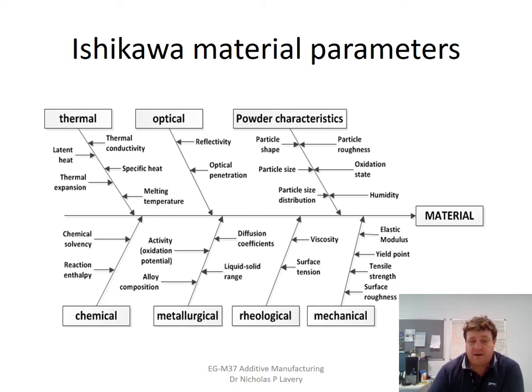Obviously, the chemical and metallurgical aspects of what type of alloy will determine how we set our machine parameters. At the level of the melt pool, the surface tension and viscosity of the melt will determine how wide the track will be, and how deep the weld depth will be for each laser scan. A lot of these will have links to the mechanical properties of the material as it comes out. So everything from the basic elastic properties all the way up through the tensile properties are determined very much upon controlling and selecting the material and the process parameters, so that we're taking into account all of these different properties.